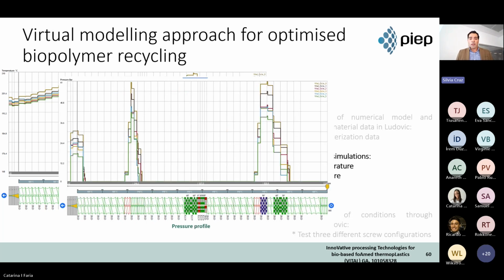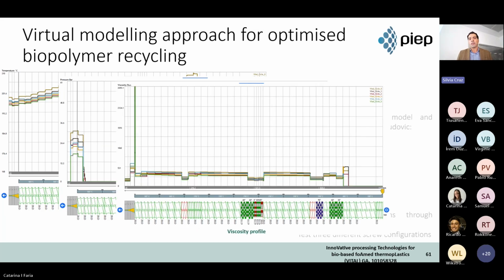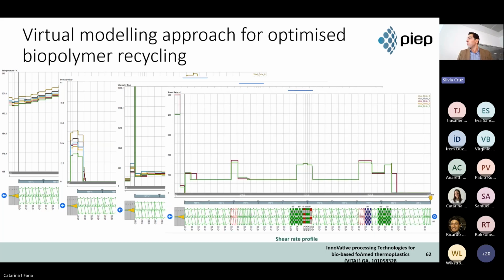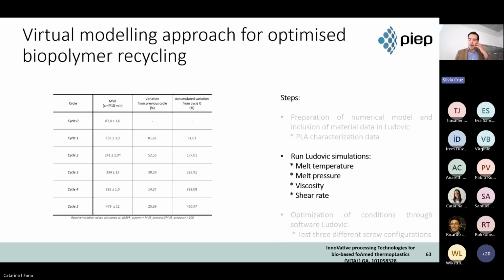If we go further, we also easily check that the pressures are changing with the reprocessing of the material. And then, of course, the viscosities are also changing when we simulate the different cycled, reprocessed materials. We also can get the shear rates, quite important because we anticipate that there is some thermal degradation of the materials, so it's quite important to monitor the shear rate that we are imposing on this material. After, I would say, the first 30 or 35 runs of Ludovic, we also characterized these materials after the reprocessing and tried to match the simulation with reality.